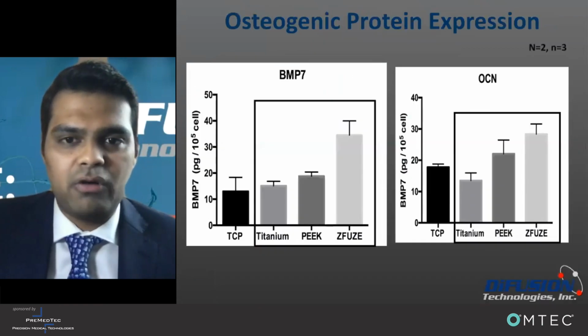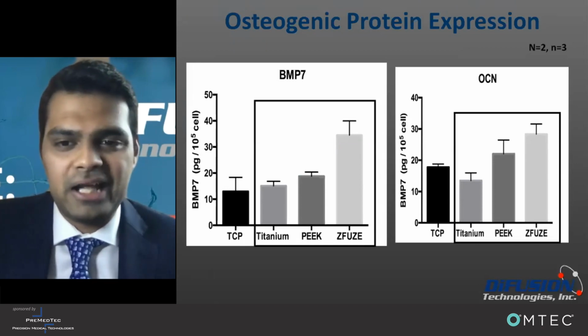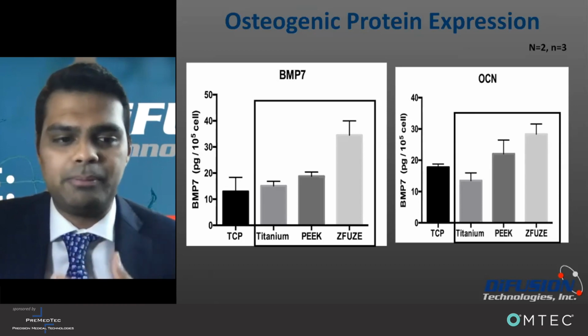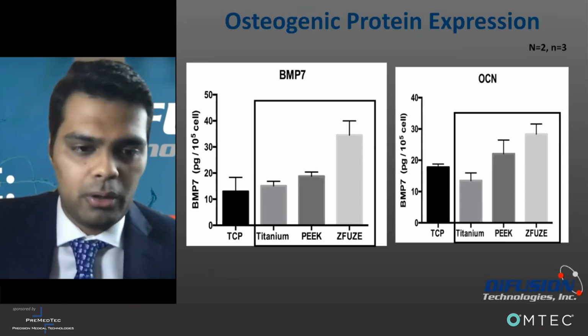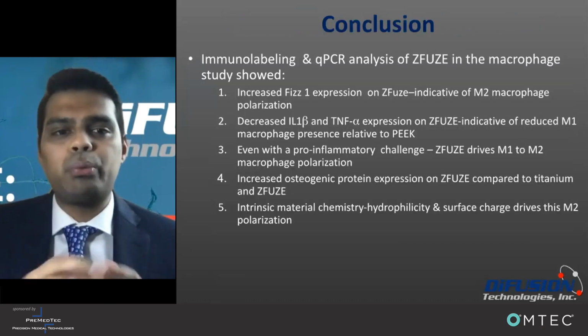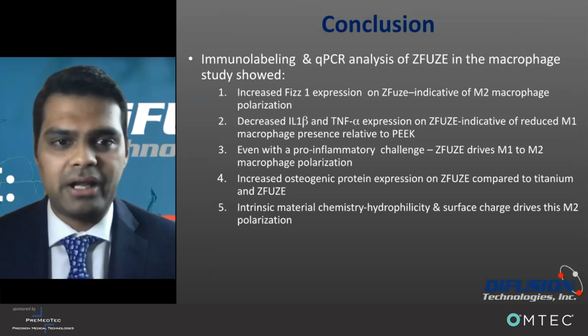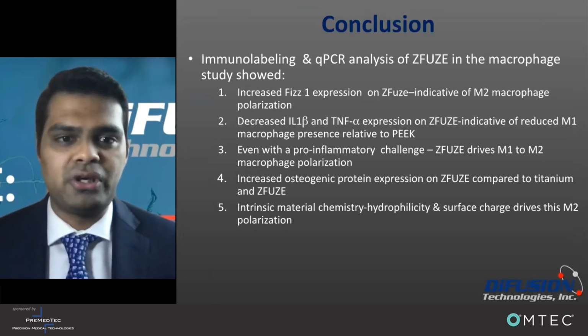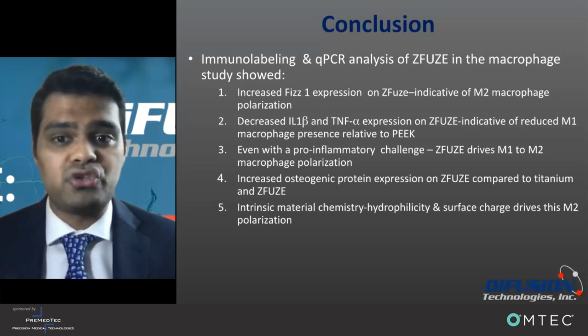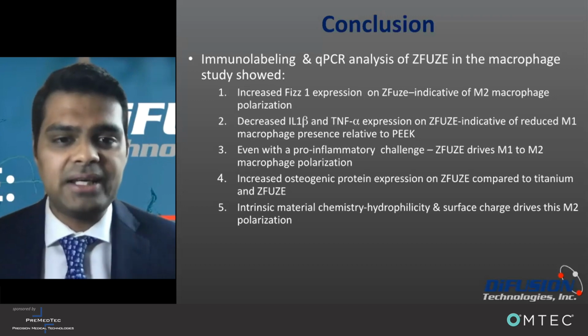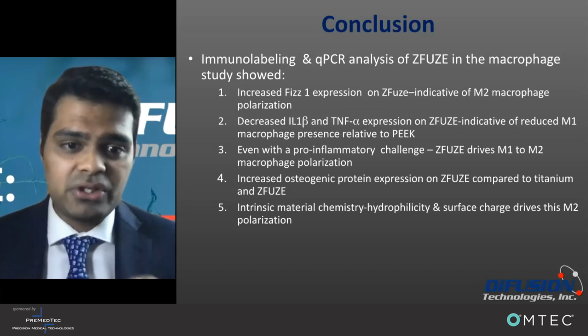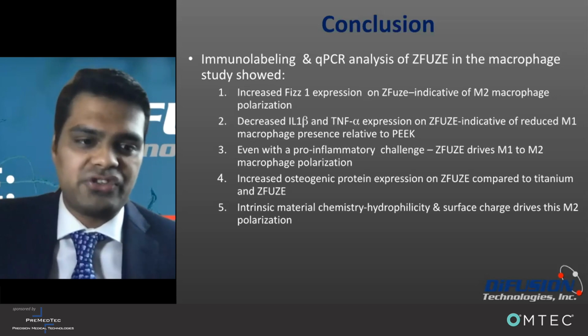Another important aspect of the protein expression was, again, we looked at BMP7 and osteocalcin, and you could see that, again, Z-Fuse outperformed titanium and PEEK on these bone response characteristics and parameters. So in conclusion, what we were able to study through the immunolabeling and PCR analysis was there was increased M2 expression on Z-Fuse relative to PEEK or titanium, decreased IL-1 beta and TNF alpha, which are pro-inflammatory cytokines. And also we found that even with a pro-inflammatory challenge, Z-Fuse drives this M1 to M2 polarization. Interestingly, increased osteogenic protein expression was seen on Z-Fuse compared to titanium and PEEK. And we believe that the intrinsic material chemistry, that is the hydrophilicity and surface charge, drives this M2 polarization.